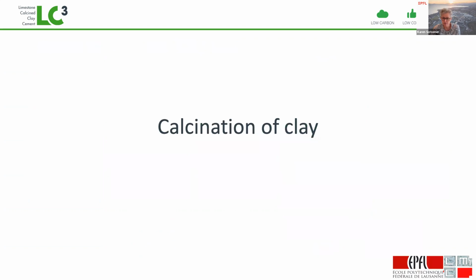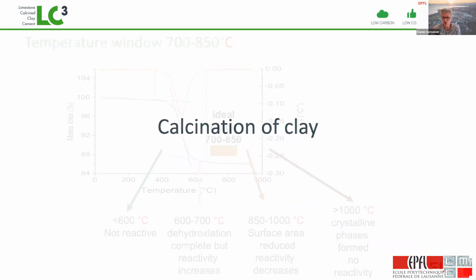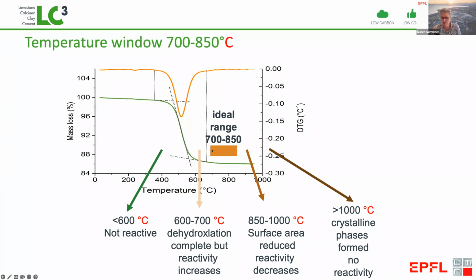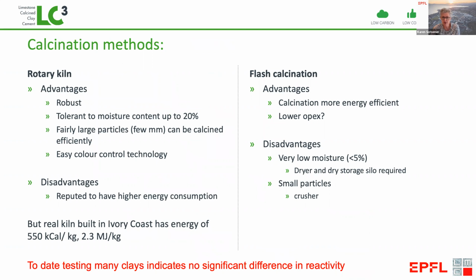Now, the calcination of the clay, more good news, it has to be done in the range of about 700 to 850. So there's quite a wide temperature region, which means the process is fairly straightforward. And we can use existing equipment. We can use rotary kilns, or we can use flash calciners. You can even retrofit existing kilns. We had a trial that took place fairly recently where only 6 hours after stopping producing clinker, they could already produce calcined clay. So if you've got excess capacity, probably the best thing you can do is convert some of your existing kilns to producing calcined clays.